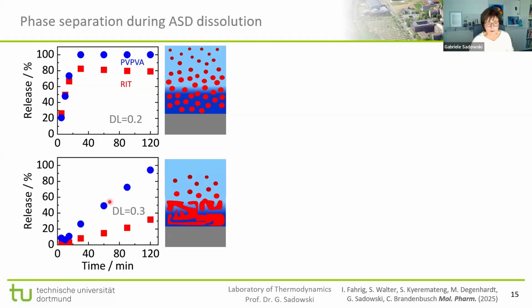For the higher drug load, 0.3, we have different amounts of the two phases, as I said before. So this is the gel phase now, and the polymer is getting released from this gel phase, but the Ritonavir-rich phase does not. This is what we have also observed in our experiments, that we have this shell forming, and after a while, once all the polymer is released, the shell will not contain any polymer, but what is left behind is the hydrophobic compound, and this does not want to dissolve. So this will stay there, and all what's inside will never get dissolved.